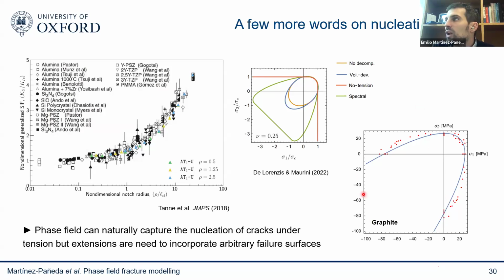However, you could have other situations. You can see graphite here. This is the case of graphite, where fractures not only occur under tension, but also under other situations. So the ability to enrich phase field models with an arbitrary failure surface would allow you to predict at the macroscopic scale when you get failures under compression behavior.